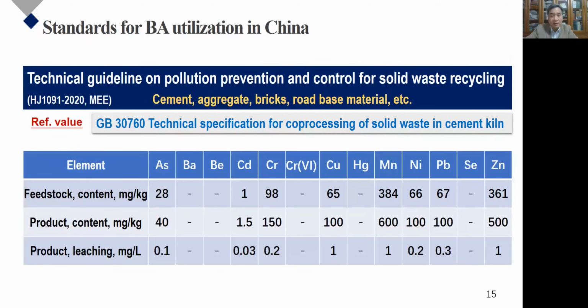This table summarizes the limit values of heavy metal contents in the feedstock and the cement product, as well as the leaching toxicity of the cement containing recycled waste. However, the limit values are recommended guidance, and this guideline is not a compulsory standard. In addition, the other products such as aggregate, bricks, road-based materials, etc. have no specific standards, so they are recommended to refer to the standards for cement from co-processing of solid waste.